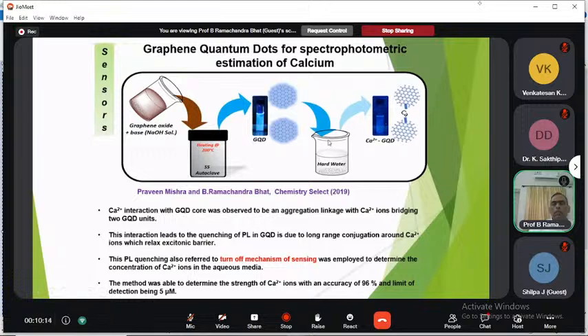Because the calcium present in water interacts with the GQD core, and it is observed that an agglomeration, or aggregation, takes place, linking with the calcium and bridging the two graphene quantum dots. This interaction leads to the quenching of the PL in the GQD. And why does it quench? Because of the long range conjugation around the calcium ions, which relaxes the excitonic barrier. So the PL quenching also refers to the turn-off mechanism of sensing.